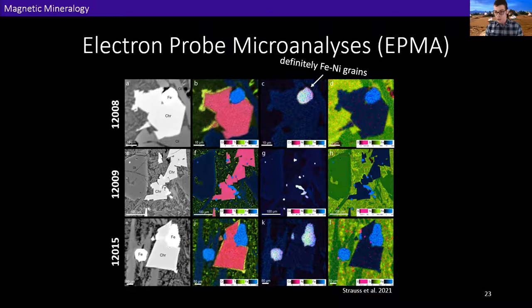And we also observed some very likely iron nickel grains of a submicron size that were unfortunately too small to acquire quantitative points from individually. So in summary, we were able to observe what we're pretty sure are multiple grain sizes of both kamacite and martensite. Again, pretty cool.